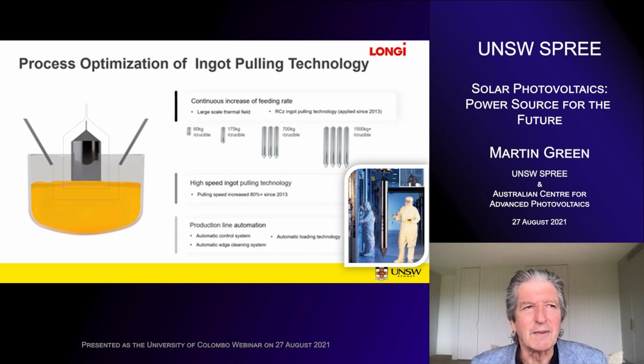So the silicon that's used in the solar cell is grown by a technique used in microelectronics. You have this molten bath of the silicon material, and you dip a seed crystal into it because you really want the silicon to have perfect crystal structure. That keeps the photo-excited carriers I talked about earlier in their excited states for a longer period. So that gives you more time to get them out, and it results in a much better solar cell if you can have that excited state lifetime prolonged as long as possible.